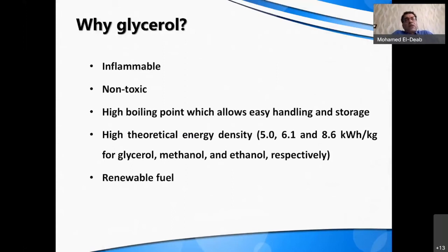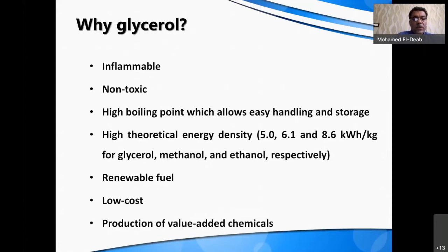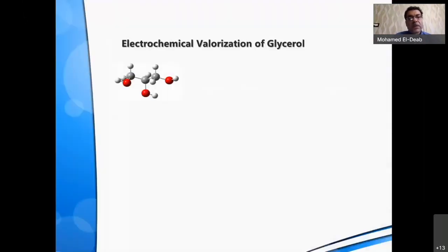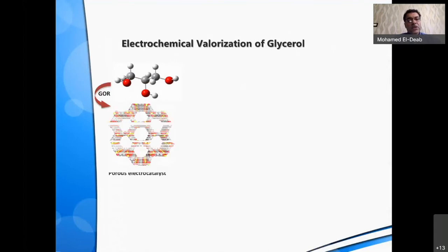For example, from triglyceride transesterification, we can produce biodiesel and glycerol as a side product, which can be used here as a fuel in a fuel cell. Also, it is low cost, and allows the production of value-added chemicals. We can oxidize glycerol into several value-added chemicals. We used some porous catalyst materials for glycerol electro-oxidation, like porous metallic layers such as copper foams, copper modified with nickel, and nickel foams also modified with some additives, and I'll show you some of our results.